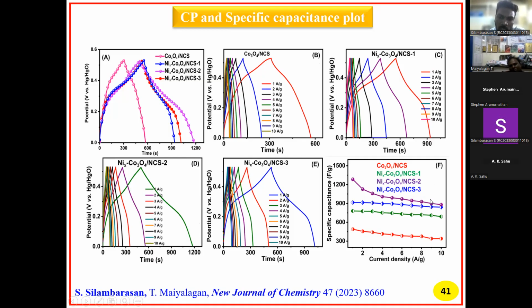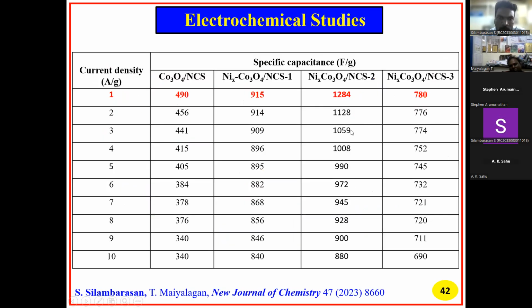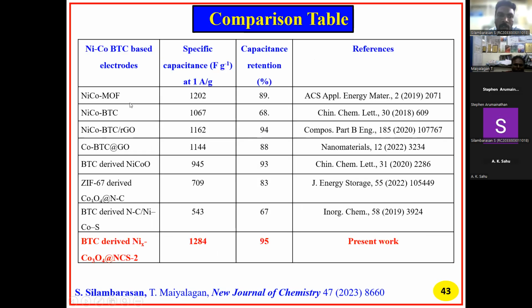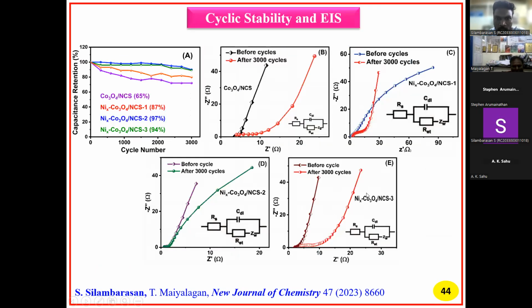Then figure F is the current density versus specific capacitance plot. Then this is the specific capacitance table. So compared to all the samples, sample 2 has 1284 farad per gram at 1 ampere. Next, we compared with previous literature our prepared BTC derived nickel cobalt oxide with nitrogen doped carbon. Sample 2 has a specific capacitance of 1284, with 95% retention.